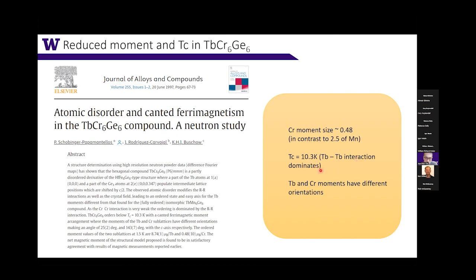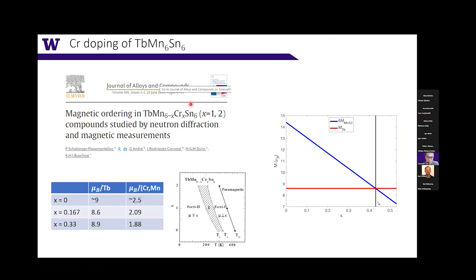So therefore, the interaction of this magnetic order is really dominated by terbium. And what I found from the neutron scattering is that the chromium moment size is about 0.48. So compared to the 2.5 Bohr magneton of the manganese in terbium manganese six six, the total moment is much reduced. So if you just slightly substitute the chromium, you're going to reduce the average moments in the chromium and manganese layer.